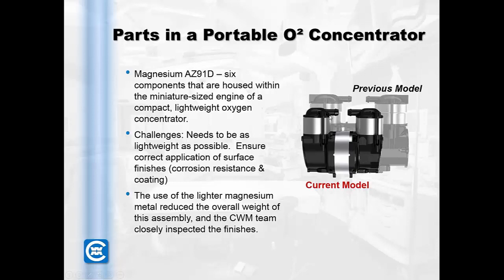You can see on the screen we show the current model. This is what's buried inside the product. This is actually a small motor, basically, that's generating the oxygen. And then you see highlighted in the background is the previous model. So you can see the size change, and with each new generation, the size and weight are coming down. Challenges for this, obviously, were lightweight and corrosion resistance, and so magnesium with an E-coat, the black that you see is an E-coat process, ends up being a fantastic solution for this product. Very lightweight, very strong, good corrosion protection, and the E-coat obviously will assist in that. But a really good application for magnesium die casting in a product.